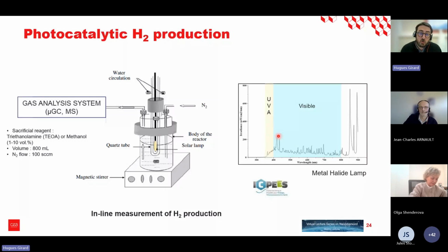So the idea is to have a gas bubbling with inert gas in the photoreactor. Then if you produce some hydrogen, you're going to be able to measure and monitor the hydrogen production using a gas analysis system, which can be micro gas chromatography, equipped or not with a mass spectrometry. The good point of this approach is that you don't have post-mortem study. You really have inline measurement of the production of the hydrogen.